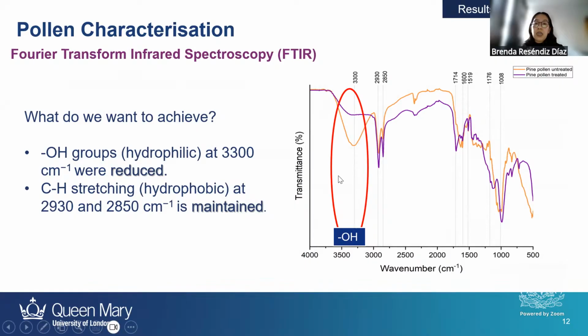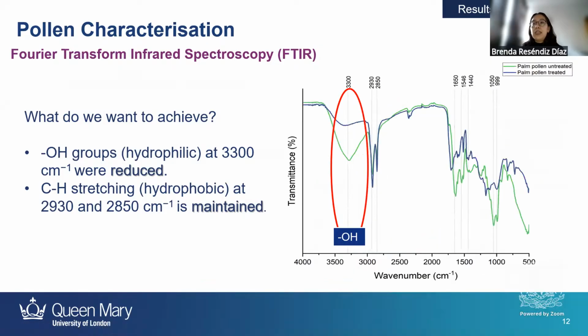So it was observed here. And we keep the two important peaks here, which are the CH stretching, which relates to the hydrophobic properties of the materials. So it was maintained at 2,930 and 2,850. Similarly, palm pollen has a similar behavior, where we maintain the CH stretching and we reduce the hydrophilic groups.